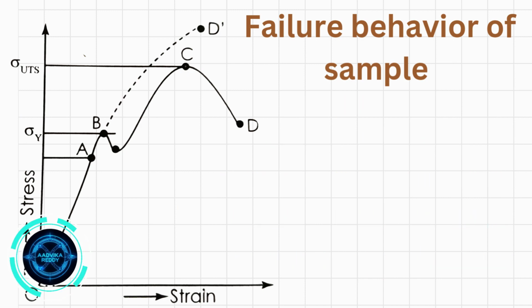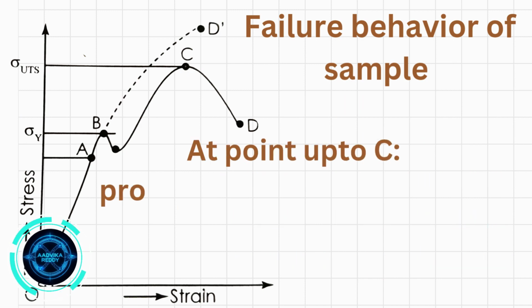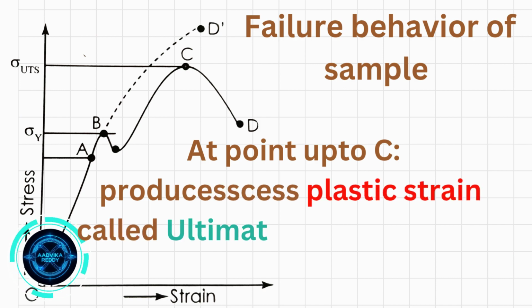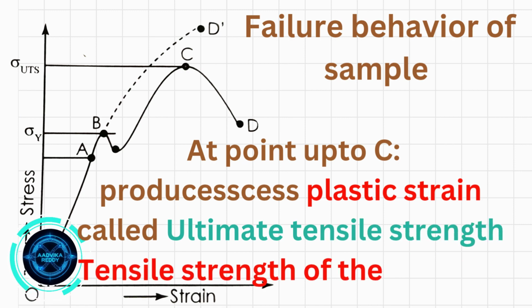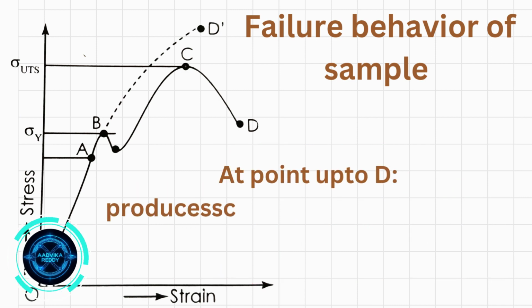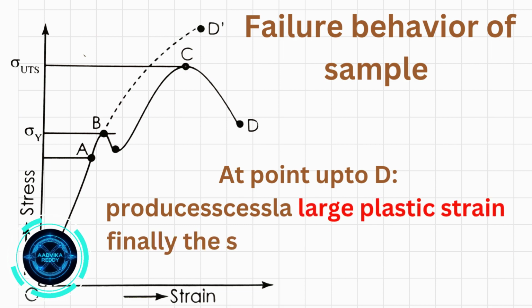If the sample is loaded beyond the point B, the displacement of atomic planes is slow, producing plastic strain up to the point C, but it will bear the elongation load. The corresponding stress at the point C is known as ultimate tensile stress, sigma UTS, equal to the tensile strength of the material. If the sample is loaded beyond the point C, the displacement of atomic planes is fast, producing severe plastic strain, where severe increase in length and decrease in cross-sectional area of the sample takes place. Finally, the sample will fail at point D.